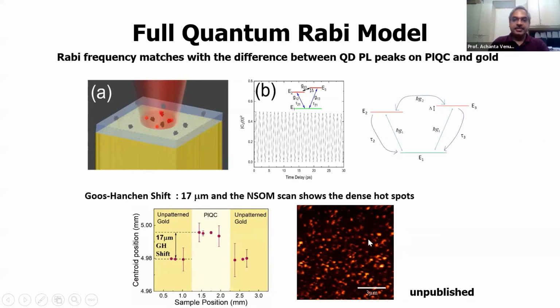hotspots on your plasmonic quasi-crystal. If you have a bunch of quantum dots here and a bunch of quantum dots here, they can interact with each other through the plasmon excitation. The emitted light is going to excite plasmons at the interface, and then they talk to the bunch of quantum dots which are here, right? So that could lead to the long coherence times which are possible in this system.